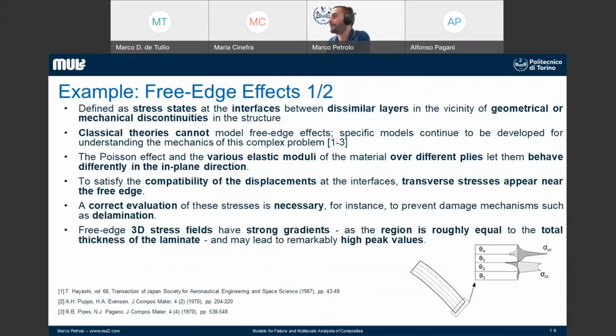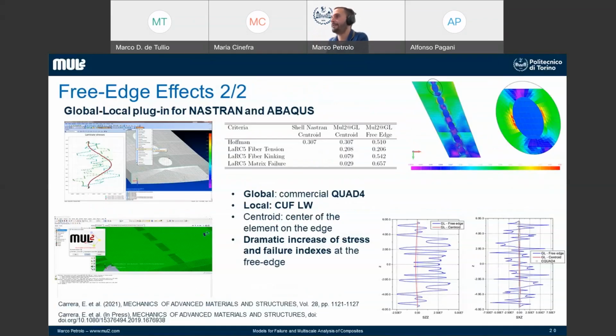Another example of physical behavior that is very difficult to model in composites is the free edge. Free edge effects take place at the interface between dissimilar layers and in the vicinity of geometrical or mechanical discontinuities. Let's suppose that this is a composite plate. At the end of the plate, if we have dissimilar layers, say with different orientations, we may have a free edge effect. Free edge effect means that you have a 3D stress state, and in that area, the stress values are very high. And we can see this in this example.